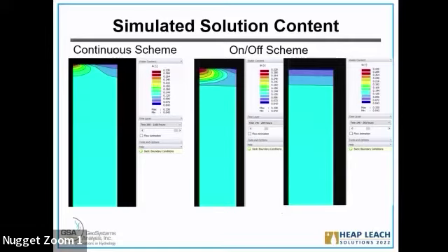This model cannot handle it, but this is just the model showing the continuous scheme. While compared to on-off, which is the power of on-off, you can put a small slug of water solution and then let the rest of the time the capillary do the action, and it will pull the water to spread, and then a very even wetting process can occur.